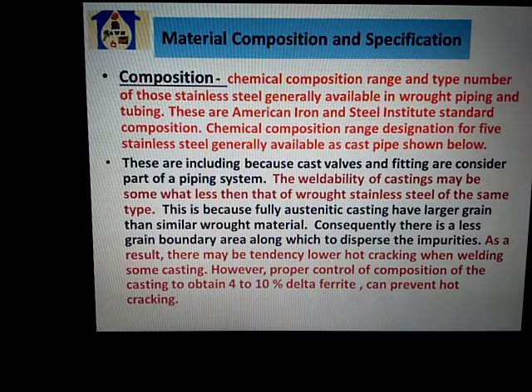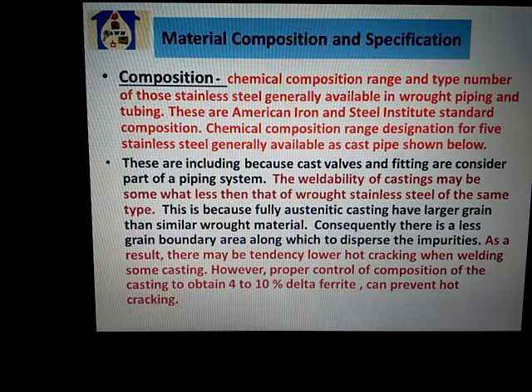The weldability of castings may be somewhat less than that of wrought stainless steel of the same type. This is because fully austenitic castings have larger grains than similar wrought material. Consequently, there is less grain boundary area along with the dispersal of impurities. As a result, there may be a tendency toward hot cracking when welding some castings. However, proper control of the composition of the casting to obtain 4 to 10% delta ferrite can prevent the cracking.